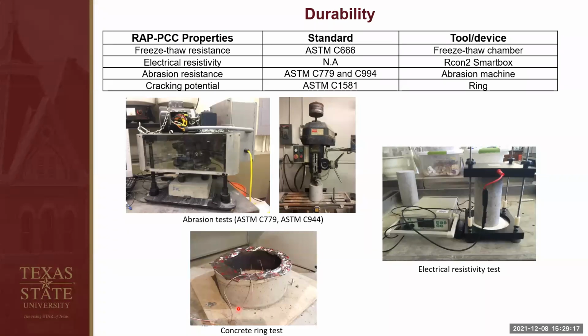Finally, we did some durability tests. We did freeze thaw resistance according to ASTM C666. We also did electrical resistivity measurements to infer the permeability of the RAP concrete. We also did abrasion resistance using 2 methods. One is ASTM C779, and the other is ASTM C994. And finally, we did a ring test to evaluate the cracking potential of the RAP concrete under restrained drying shrinkage.